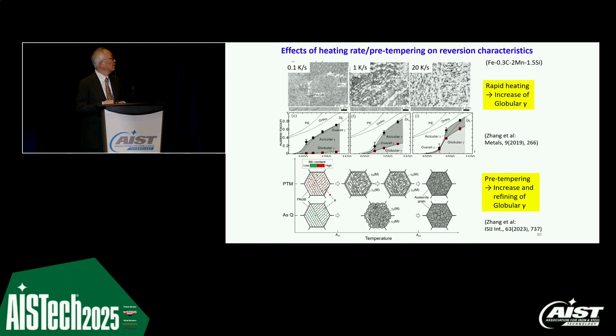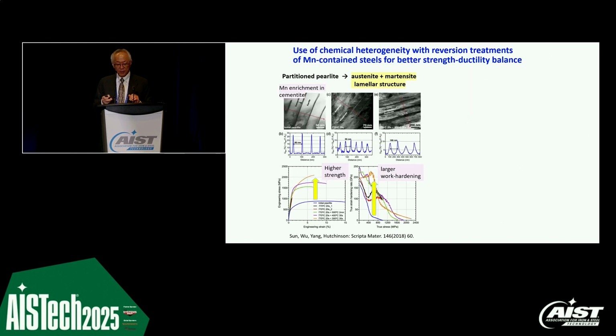Here are also two methods to accelerate globular austenite reversion. One is using tempering with rapid heating, and the other is pre-tempering. By having such pre-treatment, we can have globular austenite formed during the reversion, intercritical annealing.